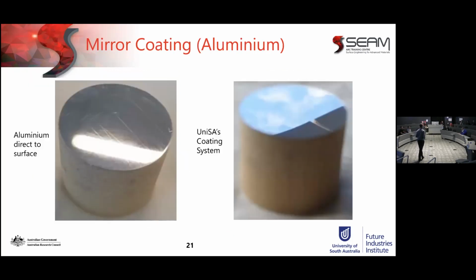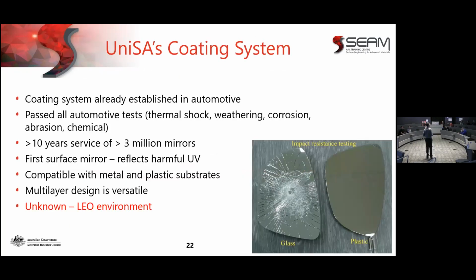So when we mirror coat it, if we put an aluminium coat direct to the surface that we've polished, we get a mirror finish, but it's cracking. So that's where the coating comes in. The image on the right is that same part that's been polished but then overcoated as well. In our University of SA coating system, it's a liquid plus vacuum coating process. So we put the liquid coating on, it self-levels, fills in voids, gaps or scratches, and gives us a mirror-like finish to then put the metal down.